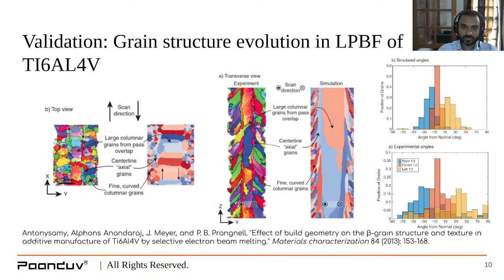given the challenging nature of such simulations, right? Another one we have is the grain structure evolution in LPBF of Ti64, and in this case we are interested in the misorientation, or the angles of each grain. So if you go on the very right hand side, the plots, you can see the fraction of grains versus simulated angle from the normal, and then on the bottom the fraction of grains and again angle from normal for experimental results. The results are quite similar to each other.